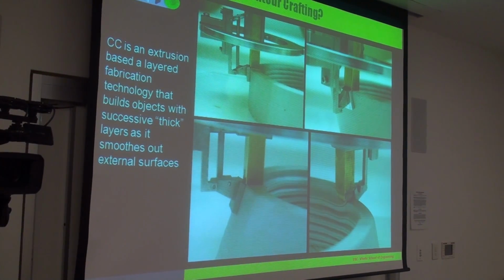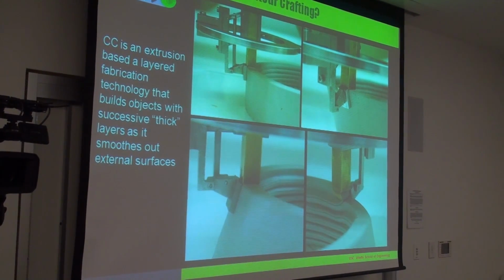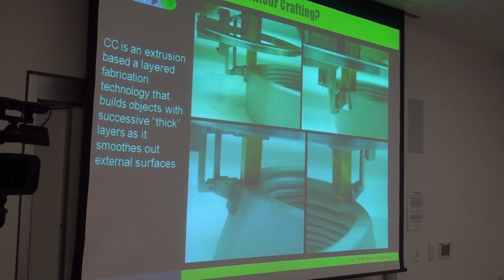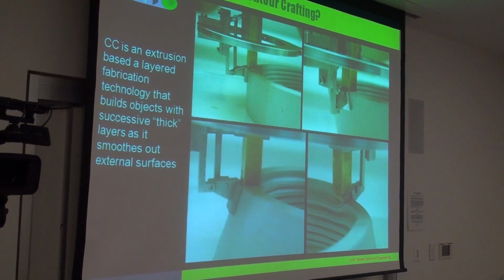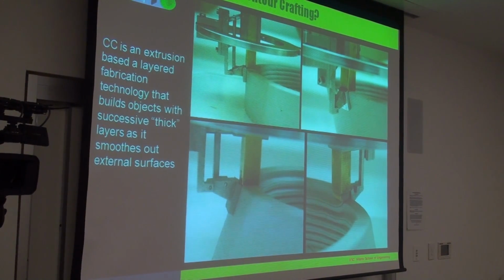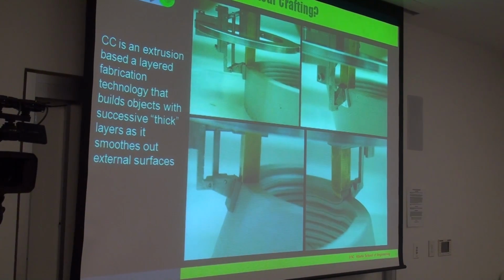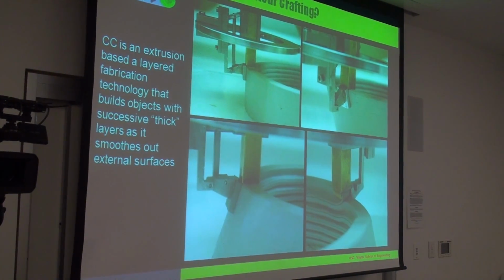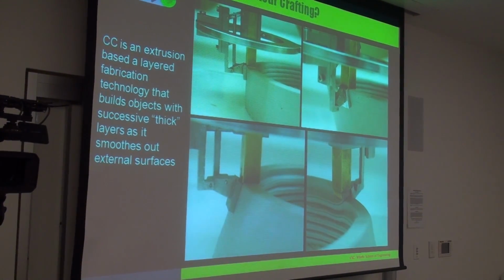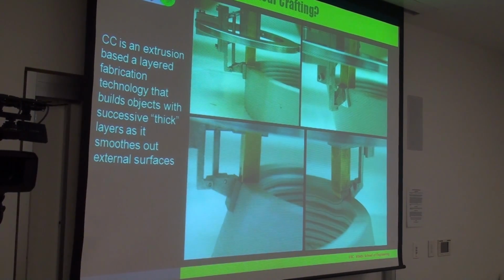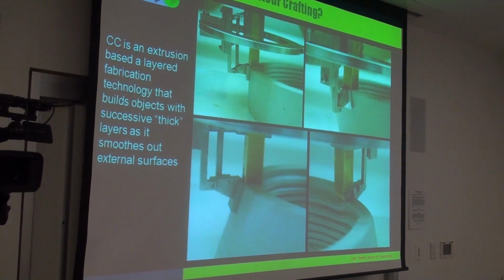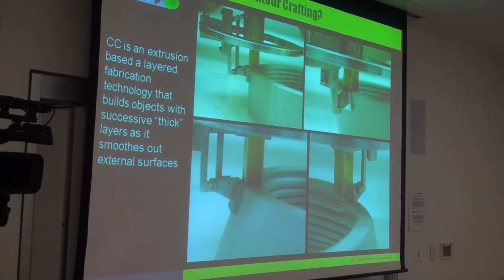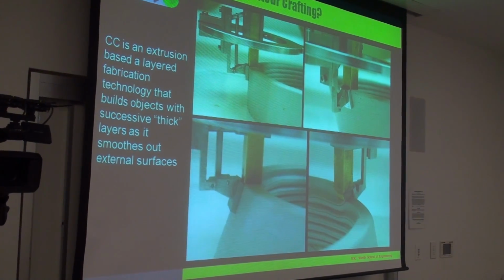Yes. So as I was filling these cracks, it occurred to me that the simple tool has great capability in producing wonderful surfaces. So then it occurred to me that if I automatically feed this trowel with paste material, and move it in 3D space using a robot, then I should be able to use very thick layers and create very smooth surfaces. Well, that's what the artisans do, don't they, actually? Right, basically, right. Exactly.